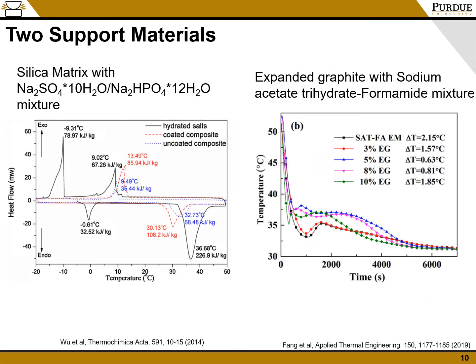Looking more into the effects of a silica matrix on hydrated salts, you can see in this study here they used a mixture of 2 hydrated salts, as well as tested a composite that was coated with a paraffin wax versus an uncoated composite. The coated composite had a higher latent heat energy than just the traditional hydrated salt mixture, which is a promising aspect to adding a silica matrix, as well as the coated and uncoated composites were thermally stable for 10 cycles, whereas the hydrated salt experienced a decrease in the thermal capabilities throughout the 10 cycles.